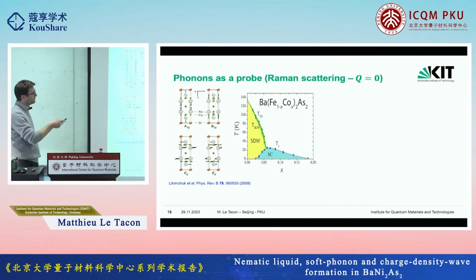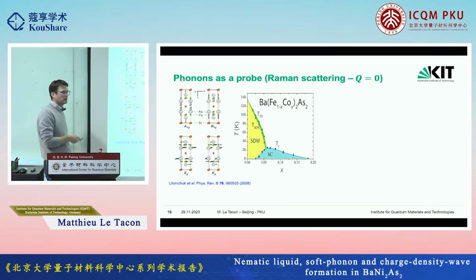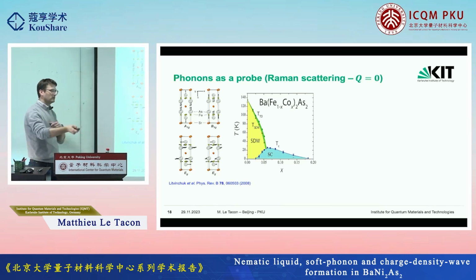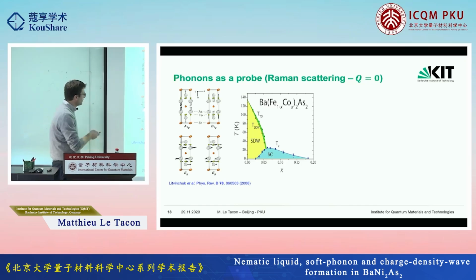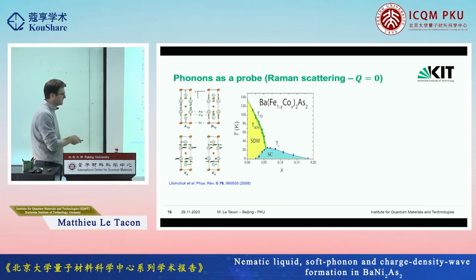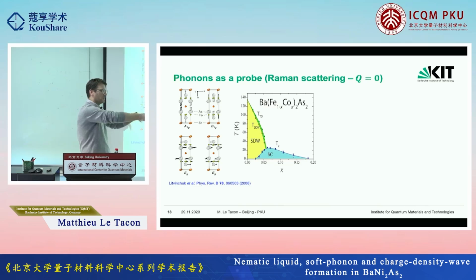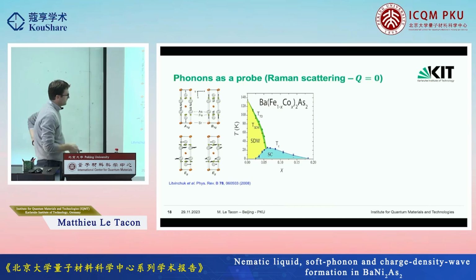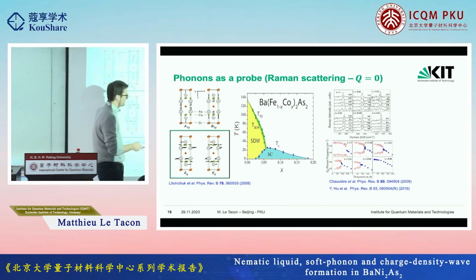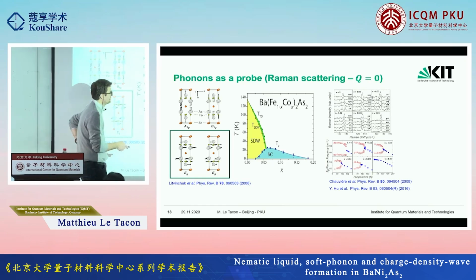Now, what happens when you go across the tetragonal to orthorhombic transition is that you lift the degeneracy between A and B. And actually, these modes are EG modes, so the E means that the modes are doubly degenerate. It means that the planar vibration along X and the planar vibration along Y have the same energy. Now, if you distort the system in an orthorhombic manner, you will lift this degeneracy and you will see a splitting of this doubly degenerate mode. So this was looked at early on by the group of Alain Sacuto in Paris, but there was also some nice work done here by Yuan.